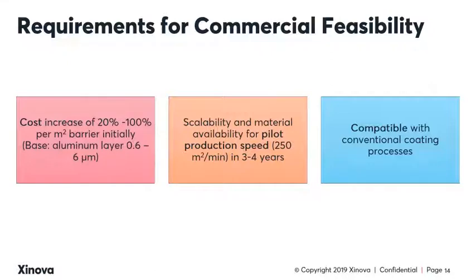There are also key requirements for commercial feasibility. So it's important to consider cost. Stora Enso has noted that they can tolerate a cost increase of 20 to 100% per meter squared of barrier initially. And to help with that, they noted that the aluminum layer currently used can be between 0.6 and 6 microns.